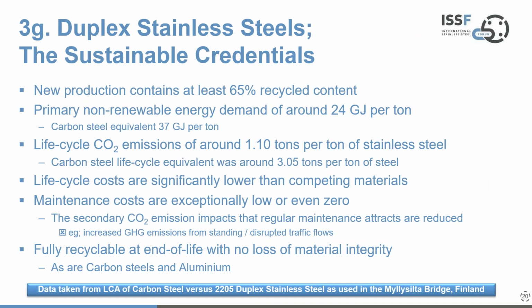I'd now like to move on and just consider some sustainable credentials, particularly of duplex stainless steels. For this family of grades, new production contains at least 65% recycled content. In terms of primary energy demand, this family of grades is much lower than that equivalent for carbon steels. The life cycle CO2 emissions of 1.1 tons of CO2 per ton of stainless steel, again, is significantly lower than